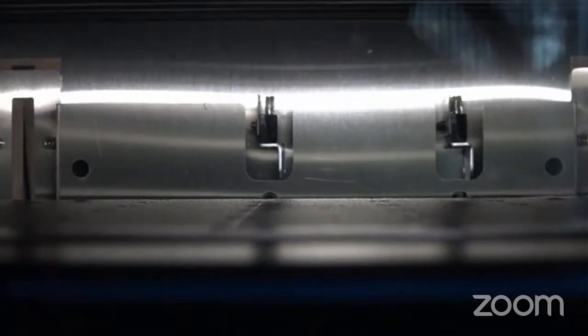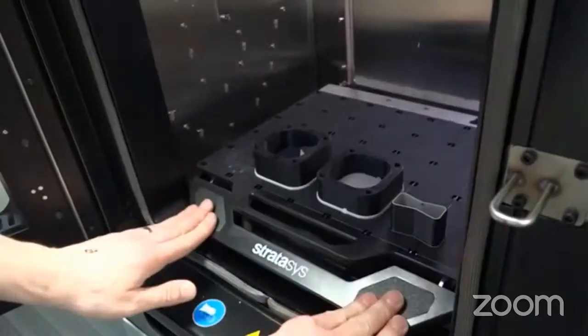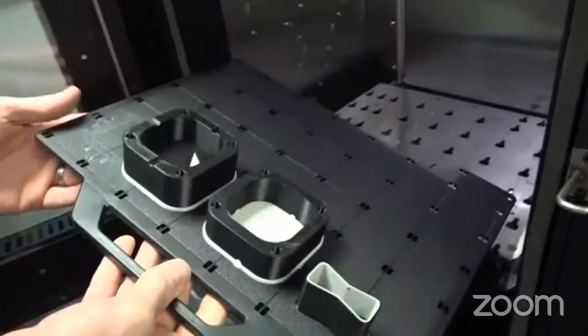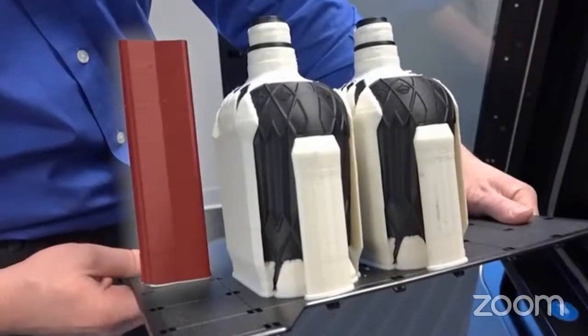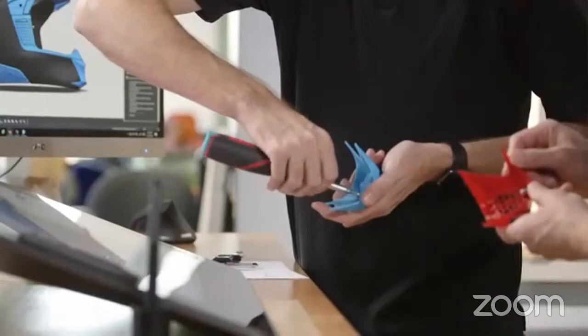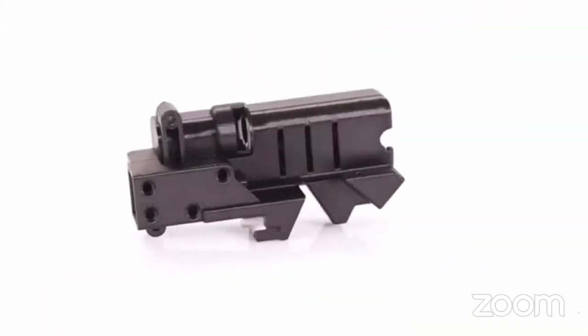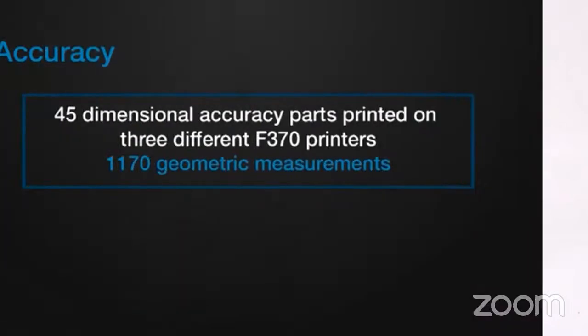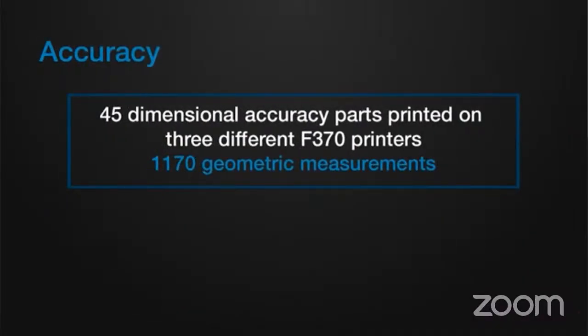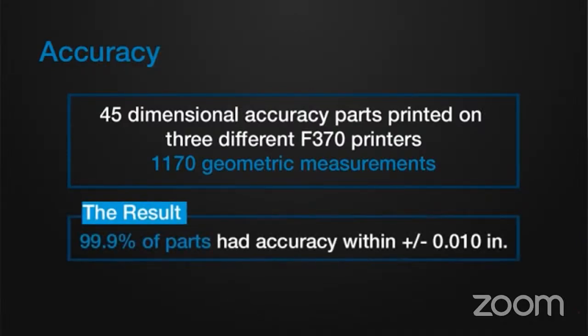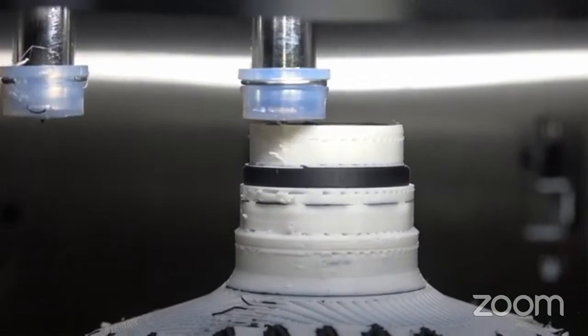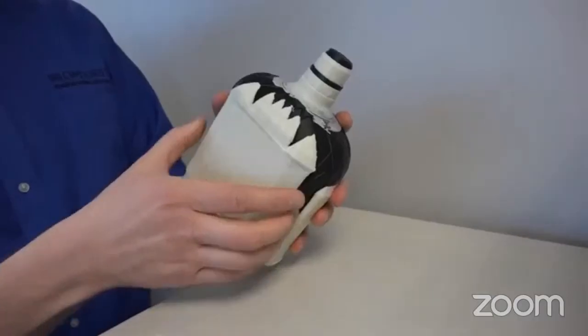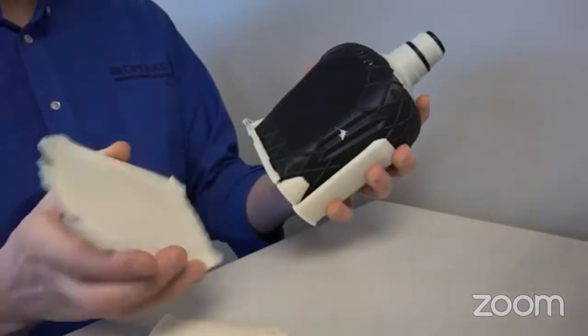In terms of the printing process, the F123 series has a newly designed print head, which eliminates the need to change tips. To control aesthetics and minimize issues related to material purging, each printing job automatically has a sacrificial tower. These machines offer a fast draft mode in PLA for inexpensive, quick models. Regarding accuracy testing on the new systems, 45 different parts were printed with varying dimensional requirements, and they were printed on 3 separate machines. The results were 99.9% of parts had accuracy within plus or minus 10/1000ths of an inch on a 5-inch part. The machines use SR35 support material, which dissolves faster than some prior support materials, but most notably, it is much easier to remove by hand.